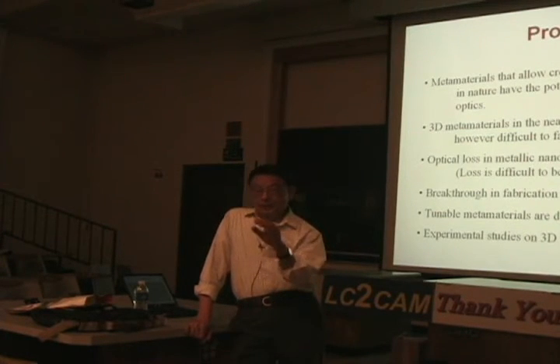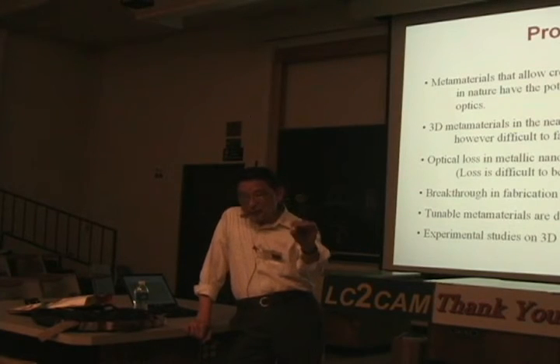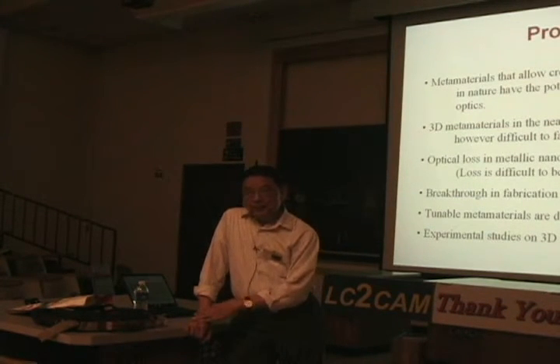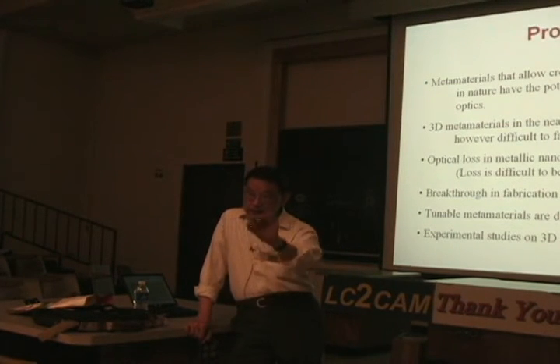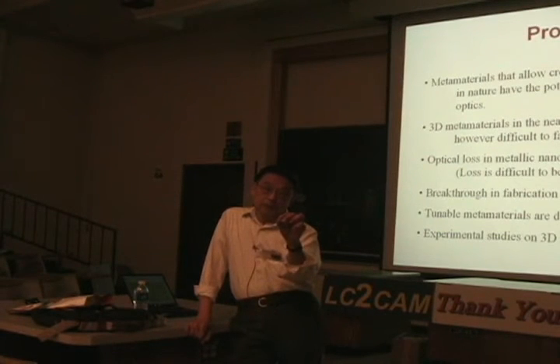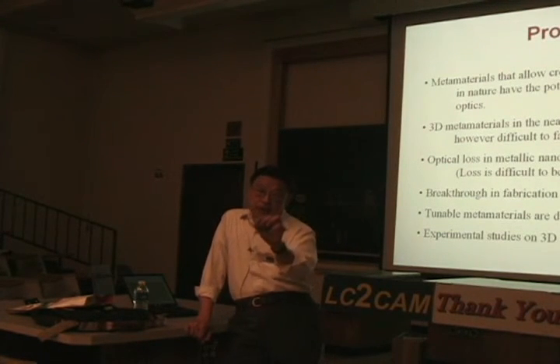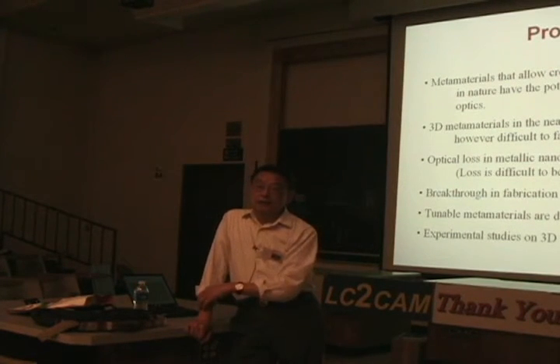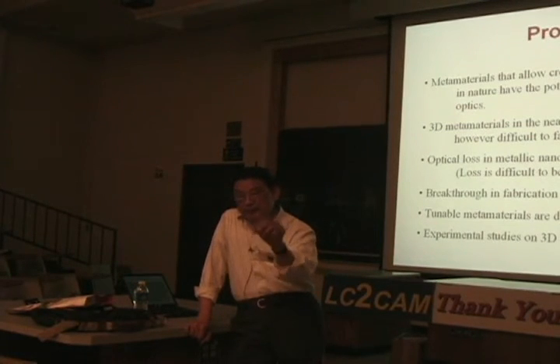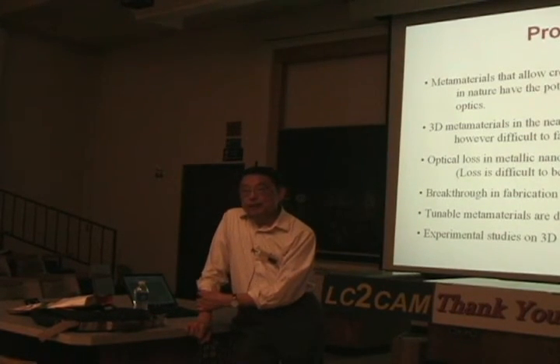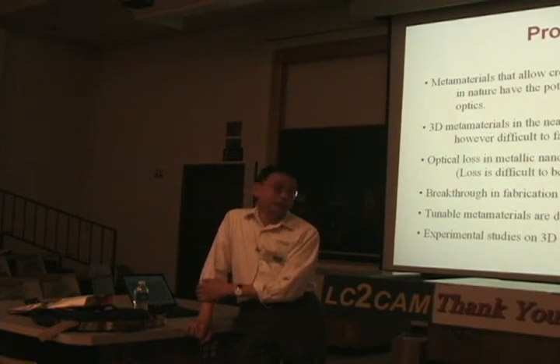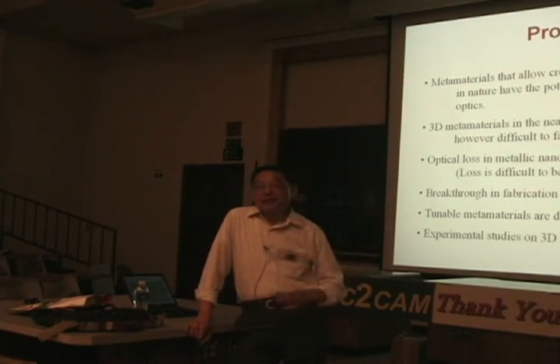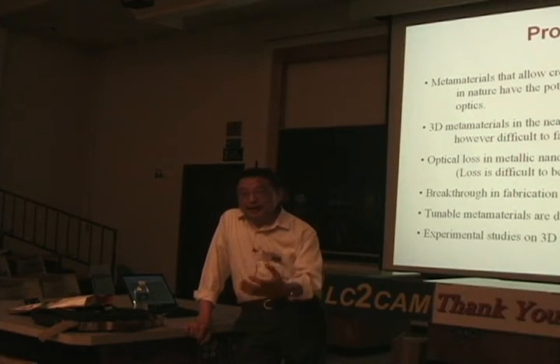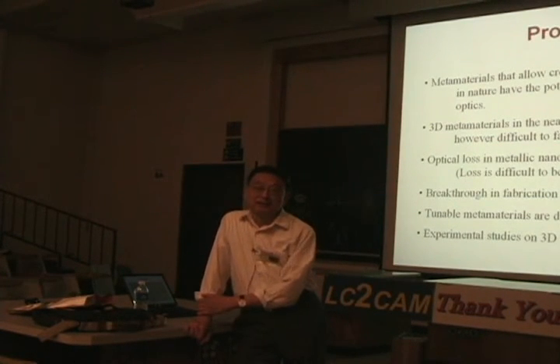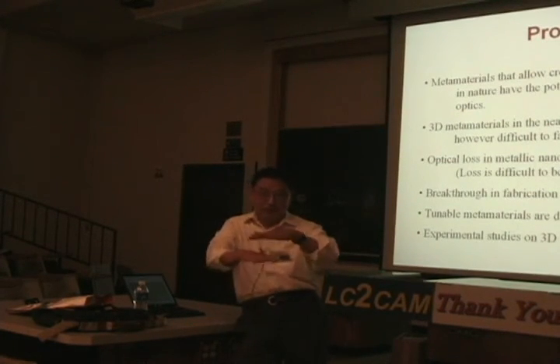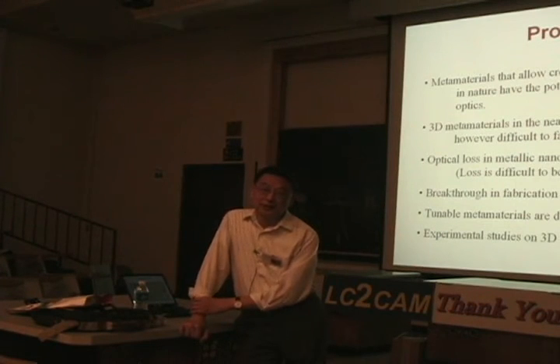Now, it's possible to also have a dielectric medium which is highly nonlinear. For example, if I put in gallium arsenide as the in-between layer, then it's possible that the nonlinearity we see will be much higher, because this chi will also be coming from the gallium arsenide. And the other thing is, you're coming from the Liquid Crystal Institute, and we want to have tunable resonance. So it would be nice if you have liquid crystal as the dielectric medium. Then you can apply the field on the metal part, and you can change the dielectric constant by just turning it on.